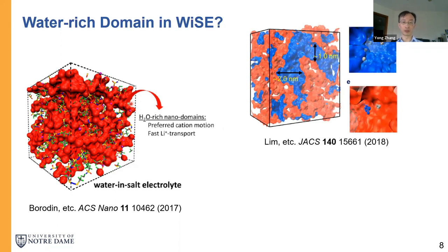A few years later, a group from South Korea did a classical MD simulation. Also, they did an IR study. So in their simulation, they see this kind of water channel is quite large in size, for example, here is 2 nanometer. So they reached a similar conclusion that the faster dynamics of lithium is because lithium can really move freely in this water-rich domain or the water channel, following a vehicular-like mechanism.